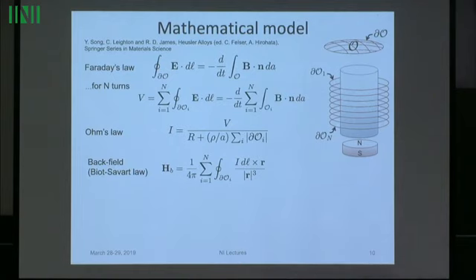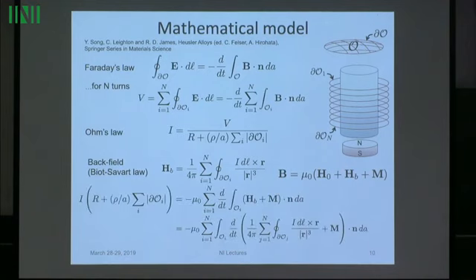Okay, so we have a voltage across the ends of this wire. We have a current in the wire, and this voltage. So in fact, I could eliminate the V between this one and this one, which is equal to B. Now, by this dipolar relation, B equals H plus M, we have two contributions to H. We have the contribution from the permanent magnet, which will cancel out, and we have the contribution from the back field. So you put the V there, you put the I there, and you put the B there, and you get this relation.